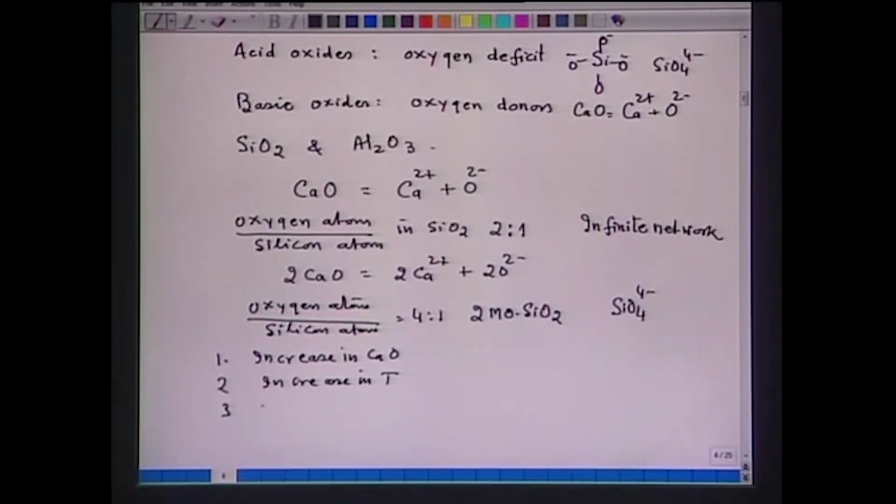Now, also Na2O or CaF2 decrease the viscosity of the slag to a larger extent as compared to when calcium oxide is added. Essentially, it is because the Ca2+ has two charges, so it will join 2 SiO4 4- ions. Na2O has a single charge, that is 2 Na+, and it will be able to join only 1 SiO4 4- ion. Similar is the calcium fluoride.